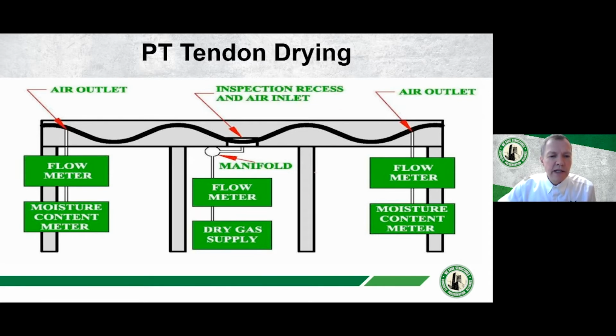So in PT tendon drying, here we're using a supply of dry gas. We're pushing it into the structure at some location, and we're either pushing it in both directions as illustrated here, or often it's pushed in at one location and out at another. But either way, you're basically pumping in dry or desiccated air at a certain location, pushing it through the tendon assembly. It's evaporating moisture that's in the tendon assembly or picking up moisture that's in the tendon assembly, and the air that is venting out here is carrying moisture that's been picked up as it goes through the system. And you continue to do that until the moisture content of the air that you're pushing out goes below a certain level that you wish to have.